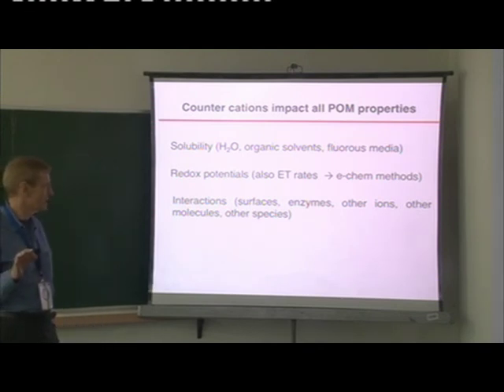Now there's all the business of interaction. POMs, including their commercialized uses — and as I mentioned in the first lecture, there are several major commercial processes now using POMs — obviously involve multiple interactions. The commercialized uses typically involve POMs as acids. You start with a heteropoly acid, where the cation is hydronium (protonated water), because water is more basic than the POM oxygens. If you remove all the water, the proton must move to the POM oxygens, making the pKa extremely low — these are super acids that will protonate almost everything, including benzene, which HCl and H₂SO₄ cannot do.